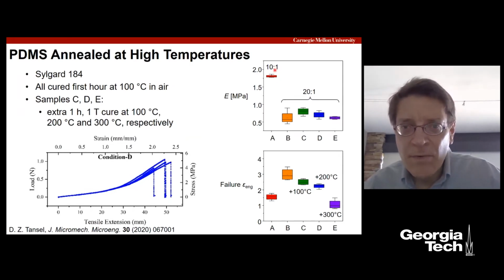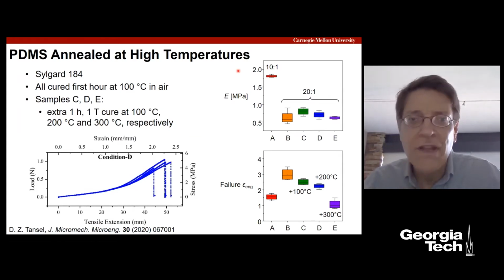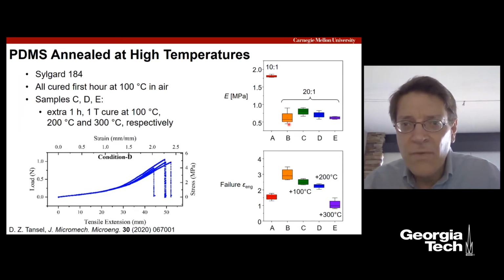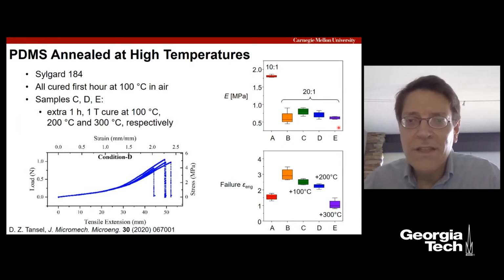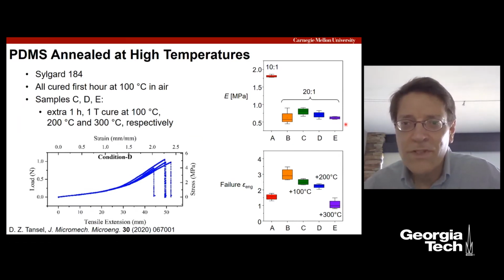We also did a 10:1 PDMS, again, just as a baseline, because 10:1 is what the vendor supplies in their data sheets. They use it 10:1. So as you might imagine, in the orange B case, 20:1 PDMS, we get a lower Young's modulus. What's interesting is that the cure in vacuum at 100 degrees C, 200 degrees C, 300 degrees C doesn't really affect the Young's modulus significantly. In fact, the Young's modulus goes up a little bit, but then it starts going down.